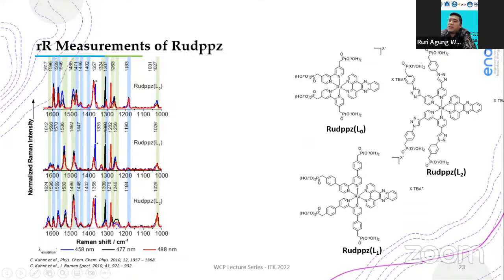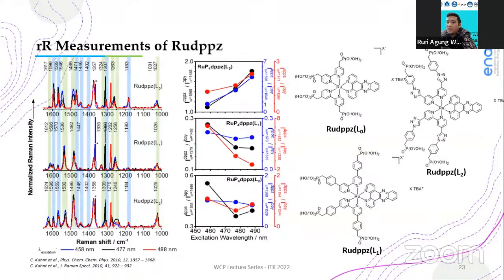So here is the intensity ratio of Raman signals assigned to the DPPZ to the PP ligands at different excitation wavelengths, which reveals the localization of the Franck-Condon region within the complexes. So for ruthenium L0, without the linkers, the Raman intensity of DPPZ increases at a longer wavelength, while it decreases for ruthenium L1 and ruthenium L2, here and here.